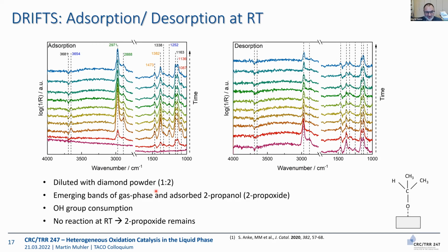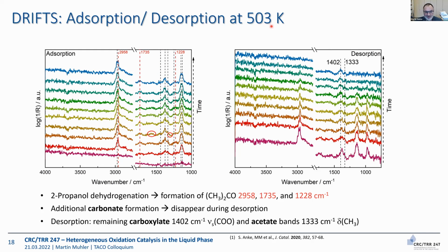When you do adsorption, desorption with 2-propanol at room temperature, then you see the formation of the 2-propoxide species. You have the 2 methyl groups that you can see nicely in the CH stretching band region. Here the CH, the CO band, that is then at low wave numbers. And this 2-propoxide species stays. When you do it at higher temperatures, 503 Kelvin, then you get reaction in addition. And then, of course, you check for the CO stretching vibration that is there. That means we do see acetone. Then we get different, chemically different methyl groups that we can distinguish, so we can clearly identify the formation of acetone and other species.